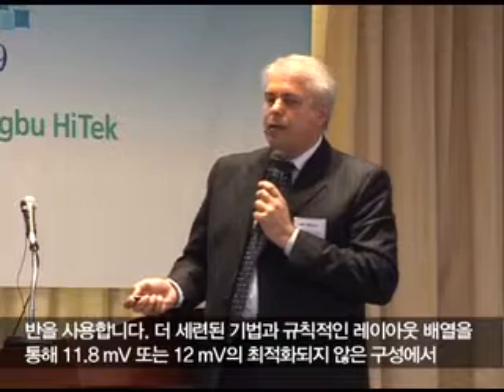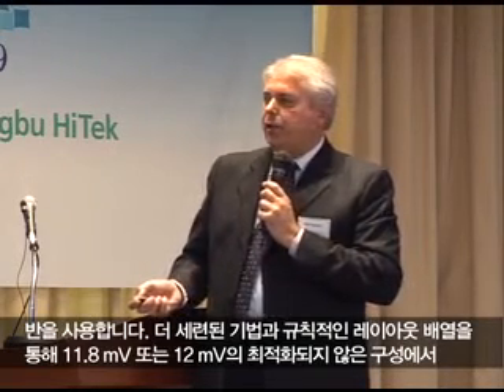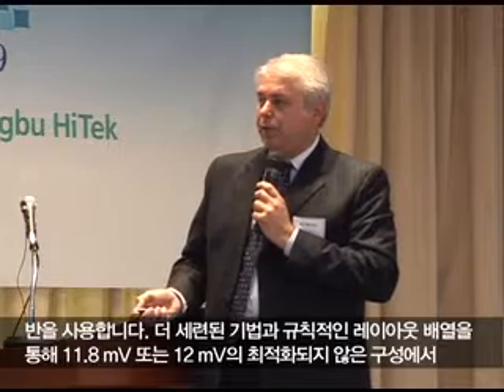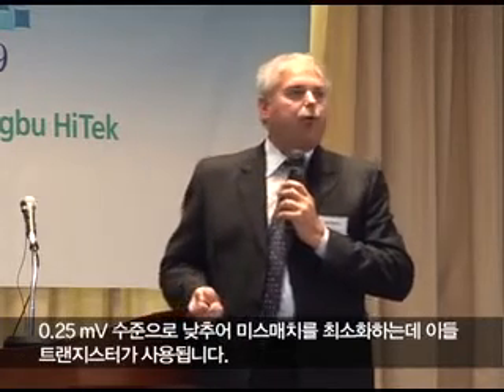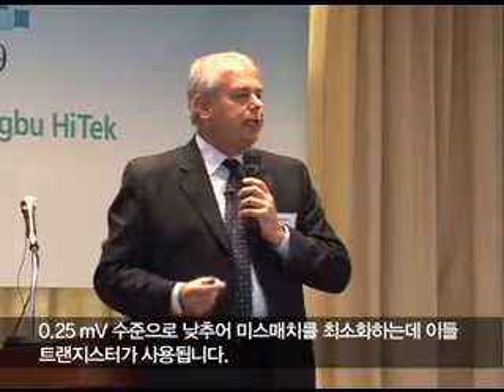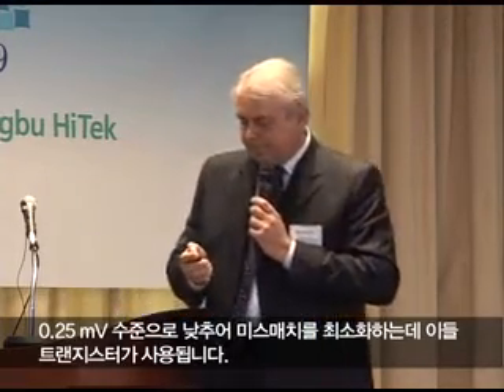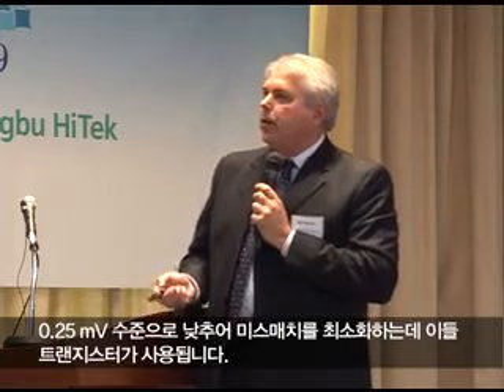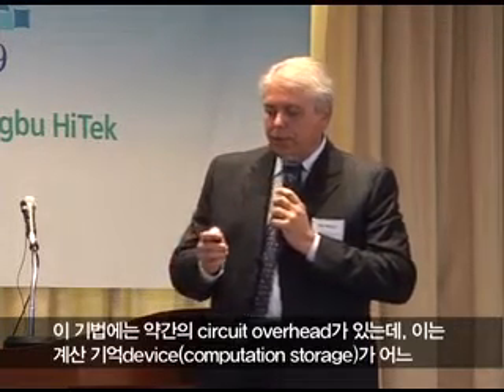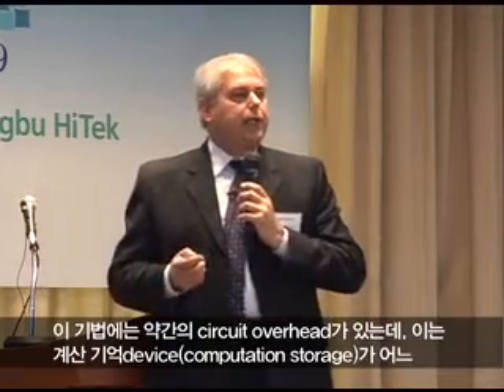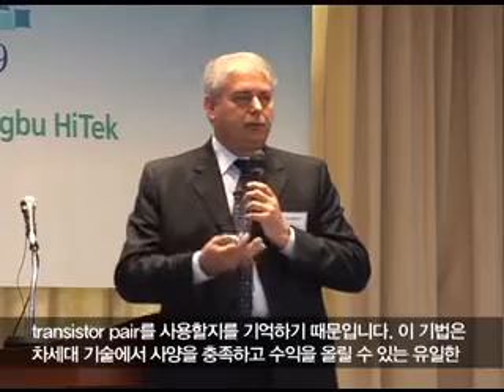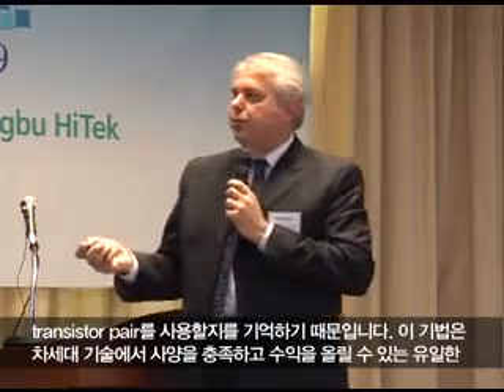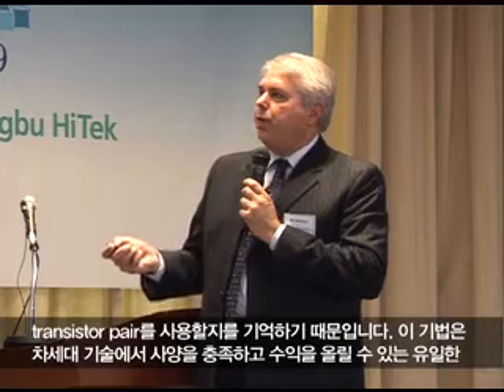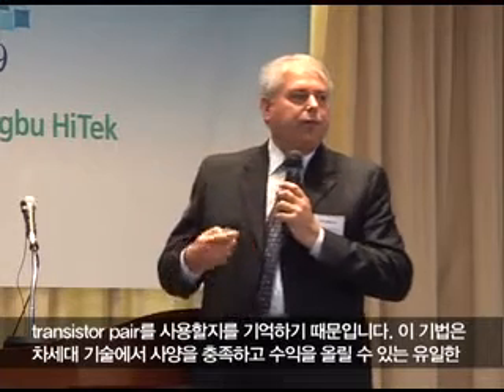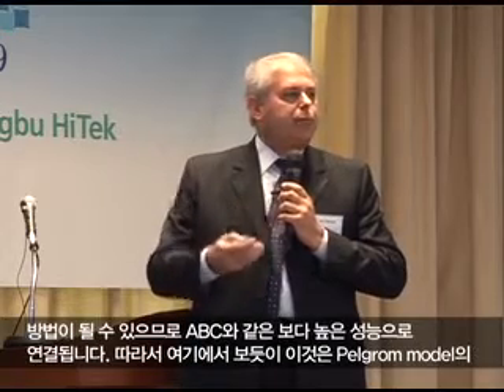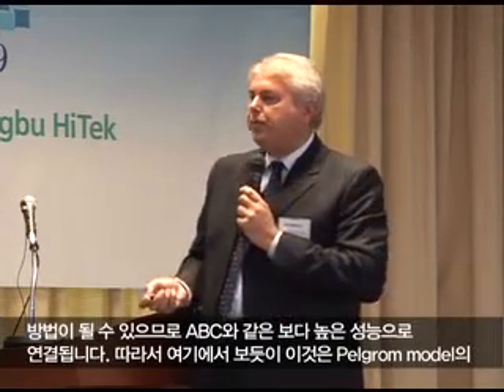And so you can go from a non-optimized configuration of 11.8 or 12 millivolts down to something on the order of a quarter of a millivolt just through these smarter techniques and these regular layout arrays. There is some circuit overhead in this technique because you are doing some computation and you're doing some storage, memorizing which transistor pairs to use. But it might be the only way to meet specs and reap the benefits of the next generation technology and make higher performance, let's say, ADC.